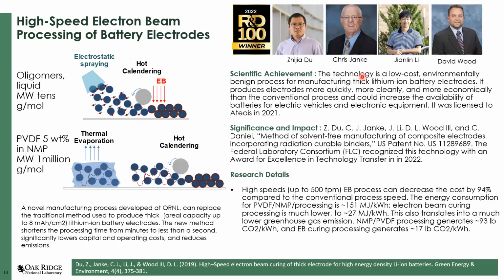So we do a lot of work on processing. Most of the current day batteries, not all, but most of the processing that is done to make these large electrodes involves using slurries made of organic solvents. It's expensive to do, and these organic solvents tend to be carcinogenic. So trying to get processes where we get rid of organic solvents is a good thing. Zhijia has come up with this marvelous idea where he has been able to use a high speed, high energy electron beam process, called e-beam curing, to make these electrodes. Again, this was an excellent idea that came from our group, and Zhijia and the colleagues got an R&D 100 award for this technology. It's currently being licensed to an external company.